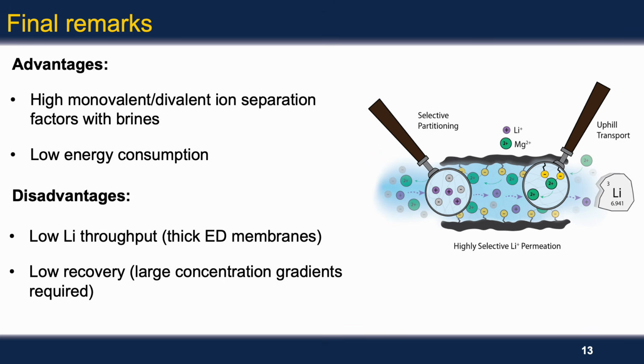In this study, we used relatively thick electrodialysis membranes, and so the fluxes were quite low. Here, one can think about designing exceptionally thin membranes, for example, like the thin film composites that are used in reverse osmosis to deal with low lithium flux challenges. Another disadvantage is the low recovery of the process. This is intrinsic, and we essentially have to maintain a large concentration gradient to have a reasonable flux across the membrane, but also to maintain the high selectivities.